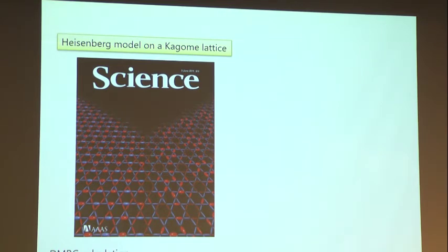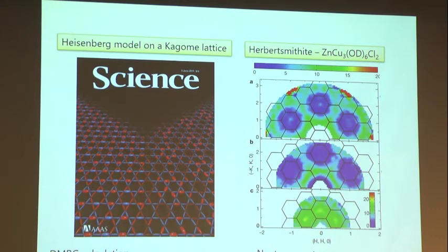And at about the same time, there was a heroic effort by Young Lee's group, who was at MIT at the time, who were able to grow a very high quality mineral called Herbertsmithite, which has the requisite Kagome lattice structure where spin-half degrees of freedom lie on each corner of the triangle. What's important is that they were able to grow very large, very high quality single crystals with very small defects, and then do inelastic neutron scattering to measure its magnetic excitation spectrum.